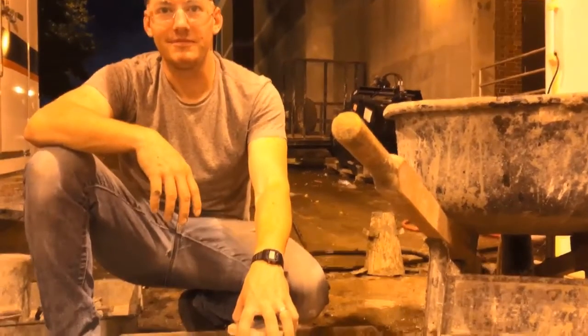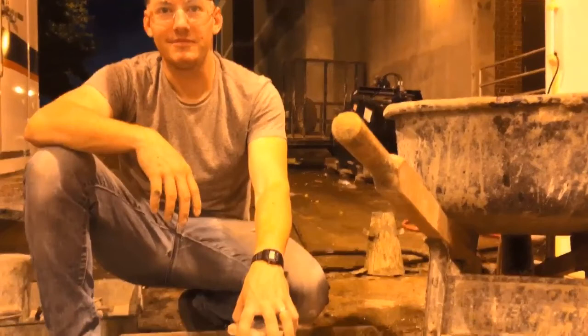So the reason why we decided to fix it after the video is just because we're trying to use this sample next week when we actually test the compressive strength. If it was all choppy like that on the top, that'd be good to report in the assignment and say that it didn't level out and it probably wasn't workable enough. The water content was probably too low. But we wanted to get a nice smooth top, that way we could actually test it right for the next video.